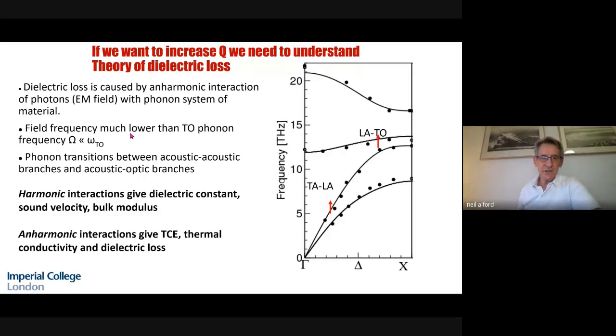theory of dielectric loss. Now, dielectric loss is caused by an anharmonic system of interactions of photons with the phonon system of the material. The field frequency is much, much lower than the transverse optical phonon frequency. And really, the things that we're particularly interested in are the acoustic transitions and the acoustic optical branches. The harmonic interactions give us the dielectric constant, the sound velocity, and the bulk modulus, but it's the anharmonic interactions that give us the dielectric loss that we're interested in.